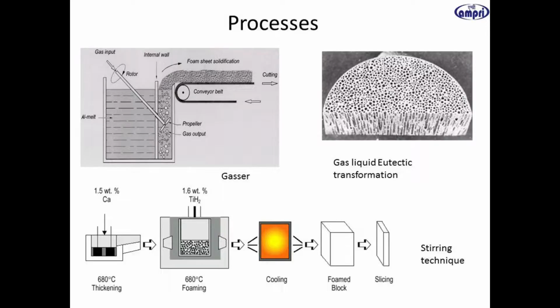Then this thickened metal is stirred, and simultaneously you have to add the foaming agent for uniform distribution. The particle size of the foaming agent is also important. It should not be of nano size, otherwise it gets coagulated and does not mix within the metal. But the size of the foaming agent should also be controlled. Some technique is there, you should ensure that the foaming agent has gone inside the metal, so some kind of modification should be used for adding this foaming agent within the metal.